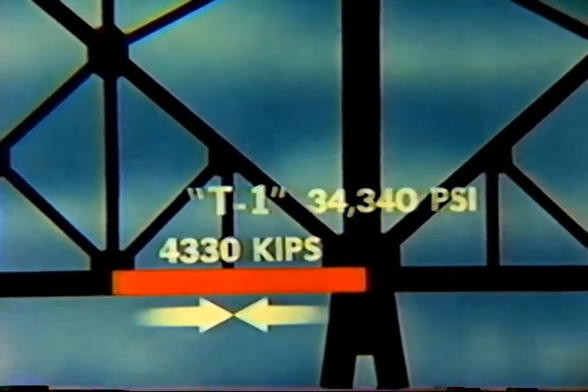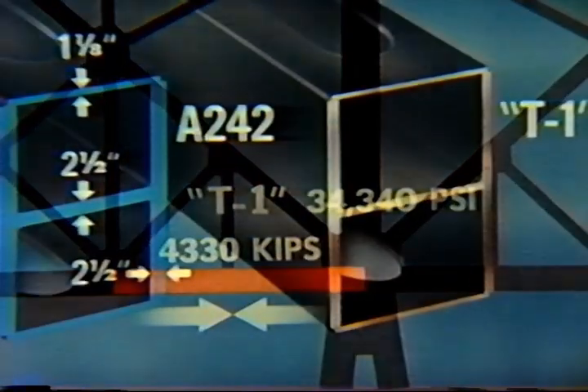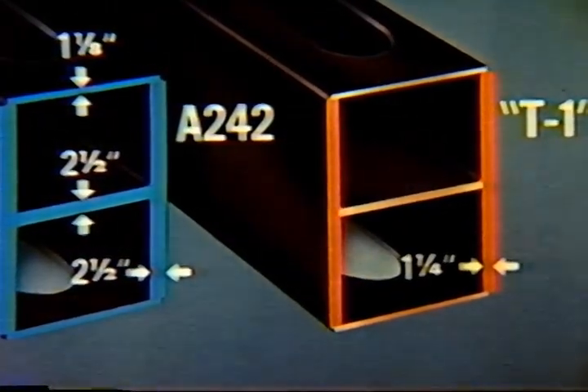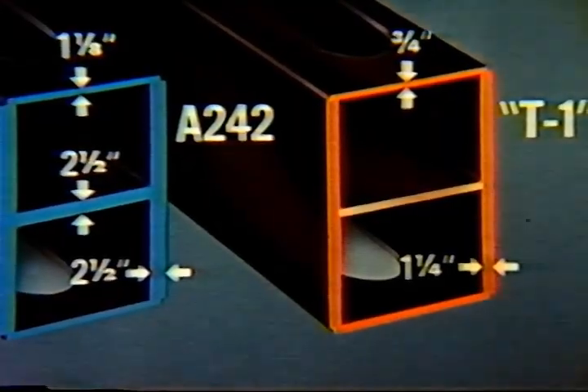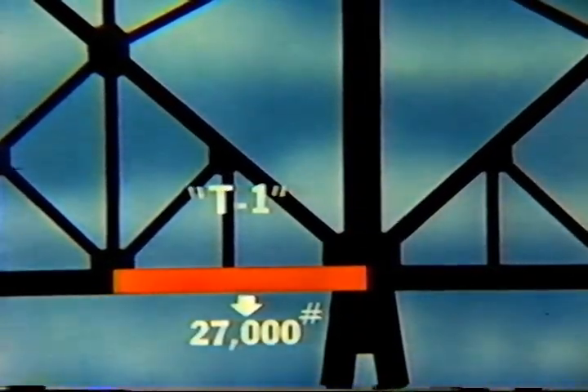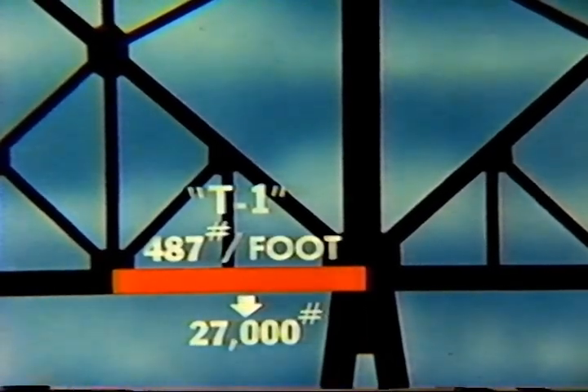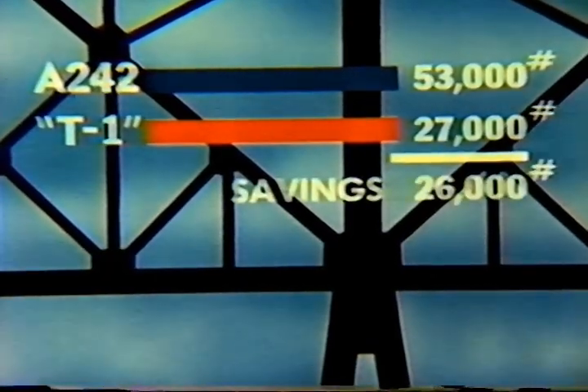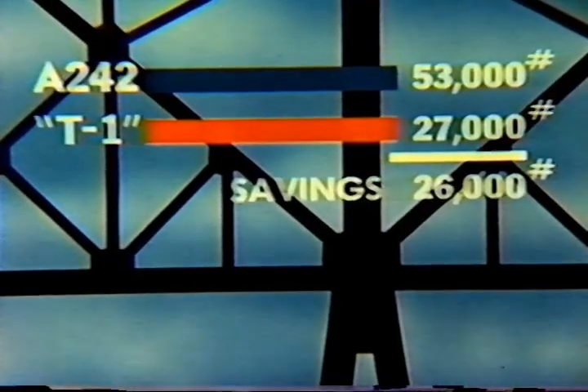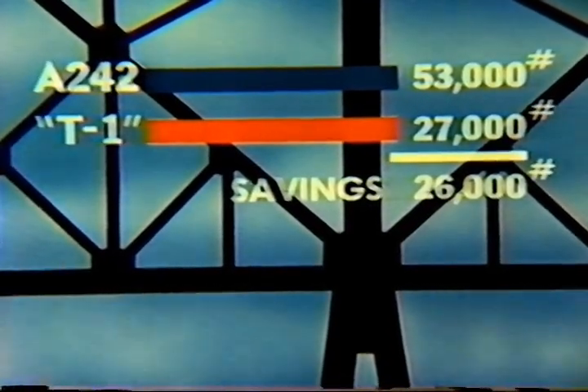But by using USS T1 steel at an allowable stress of practically twice as much, 34,340 pounds per square inch, and with a lower loading due to the reduced weight of other members, thicknesses of plates become 1 1/4, 3/4, and 1 inch. This USS T1 member weighs only 27,000 pounds, only 487 pounds per foot, representing savings of 468 pounds per foot. A total weight savings of 26,000 pounds for a single member. Such savings offered highly attractive design advantages for T1 steel.